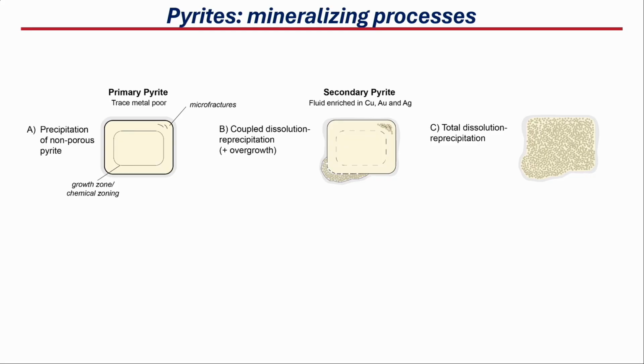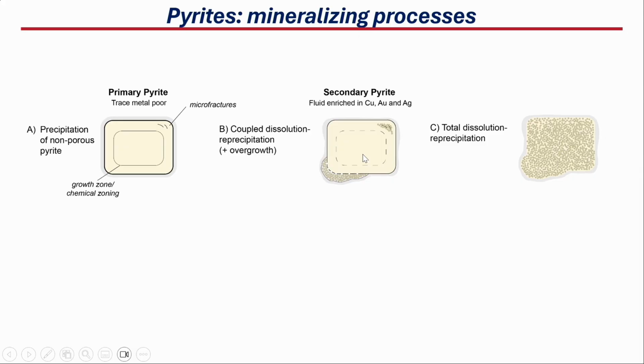So in an initial stage, we have a primary pyrite, which is trace metal poor. So we have precipitation of non-porous pyrite with some microfractures or growth zones, internal zoning, or any internal channel that represents a weak area. In a second stage, we have coupled dissolution reprecipitation plus overgrowth, as you can see in the image. And that process will affect mainly these weak areas. In a later stage, once it's more pervasive, we will have a complete or total dissolution and reprecipitation.